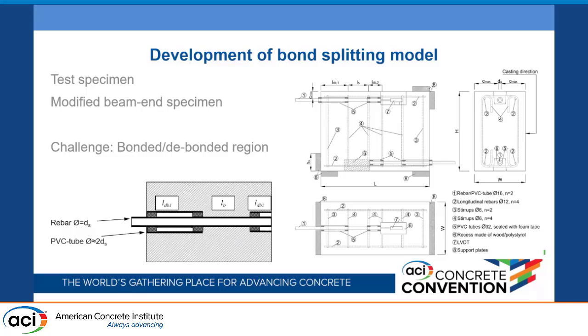So we came up with the idea of what we call the modified beam end specimen, which is now also included in the EAD. So the basic concept of the beam end specimen we took, and then the PhD student at that time, Justus Rex, developed a nice concept for these kind of specimens, where we have a debonded length in the front, then we have a bonded length, and then again a rear debonded length, and with the recess that would allow the rear end slip control, and so on. So with this specimen, we could easily vary the concrete cover, the transverse reinforcement, the concrete strength, and also the debonded length, and so on.